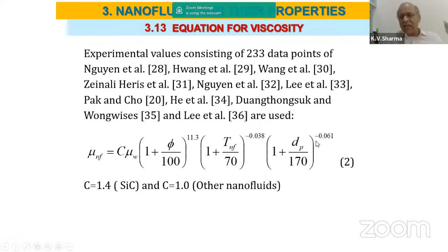And if the particle size increases, the viscosity decreases. So for a particular concentration, if the particle size increases, the number of particles will be lower and hence viscosity decreases. And here, this equation is valid for all nanoparticles, nanofluids. C has a value of 1, but only for SiC, silicon carbide, it is found to be 1.4. So please note that this equation can be used only for water-based nanofluids, not for all.